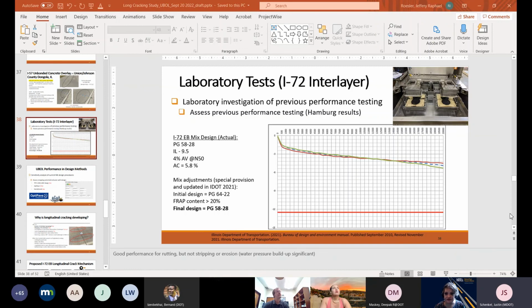Anyway, just a footnote regarding the Gratiot Avenue project in Michigan. We actually had some issues with some thin concrete sections out there. Particularly at the driveways and some intersections, they were lower than our specified thickness. So I think that was part of the issues we were experiencing with some of our cracked slabs. I think you mentioned in your table that maybe not all these issues are related to the interlayer, but at least some of our issues may be related to not getting the specified thickness.